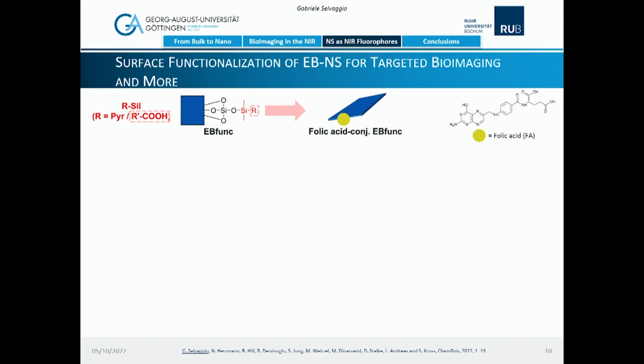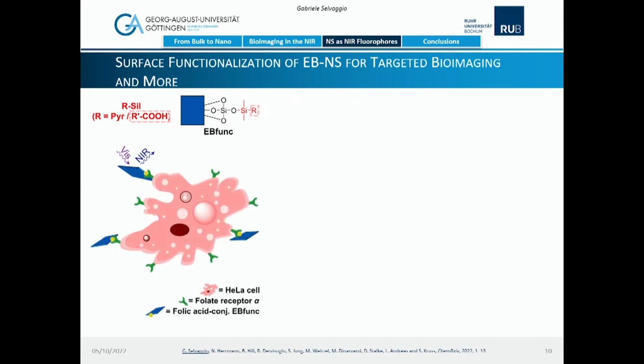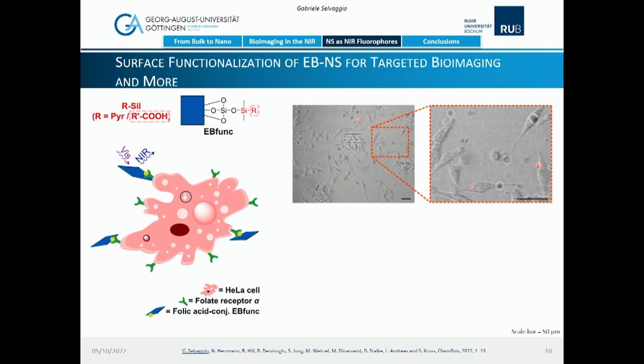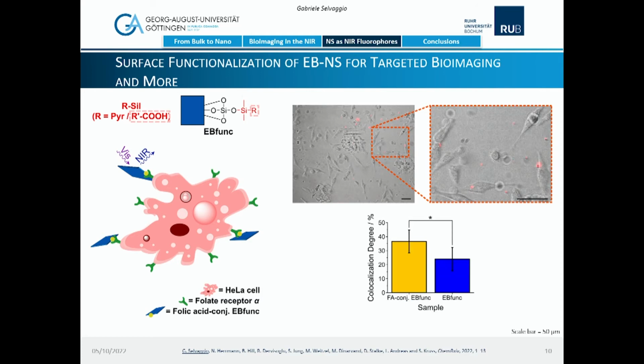And in this way, this conjugated structure was then introduced into cell lines, so cancer cell lines, HeLa cells, which are known to express the folate receptor on the membrane. Therefore, the idea is to target these receptors with the folic acid bond onto the nanosheets and do colocalized imaging, so targeted bioimaging. And as you see here in grayscale, these are the cells, and the red spots are nanosheets of Egyptian blue. And compared to the control, there was a significant difference in terms of colocalization, meaning that we were able to perform targeted bioimaging with functionalized nanosheets of Egyptian blue.